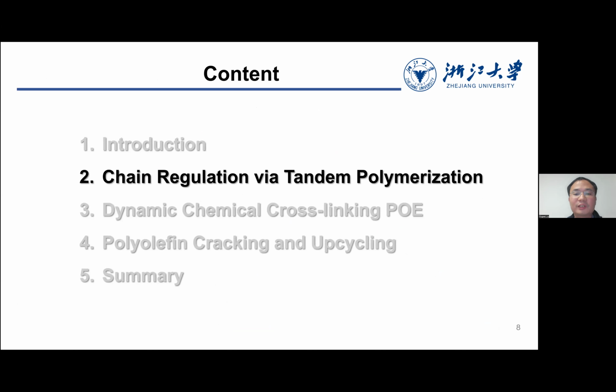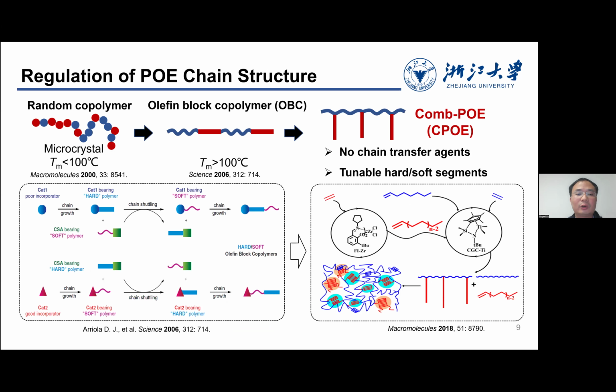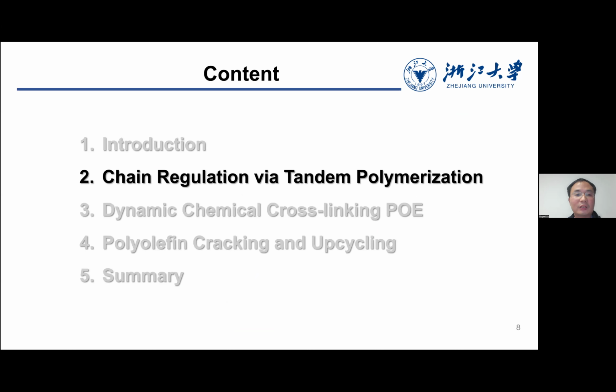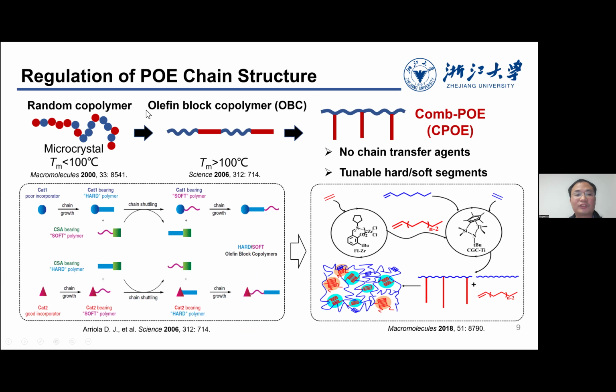work using tandem polymerization to do chain regulation of these polyolefin elastomers. If you consider the chain structure of these polyolefin elastomers, the simplest one is a random polymer. You have some segments that can crystallize, and the same chains have highly amorphous segments, and you can form a POE. And if you tune the structure to have a block, for example multi-block chains, then you can have a higher melting point, and their performance will become better.